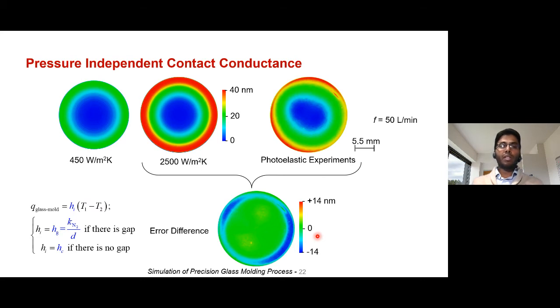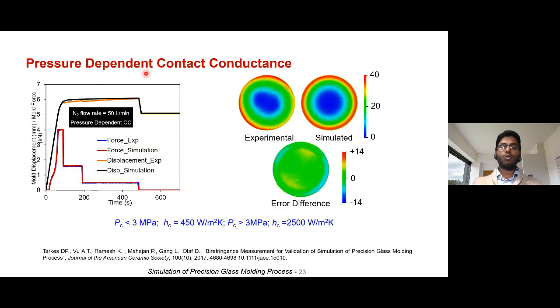But when we use pressure dependent contact conductance, as the pressing operation is being done, based on the contact pressure, we change the contact conductance value. We found out that for a critical value of 3 MPa, if you use a lower value below it and a very high value beyond 3 MPa, then we are able to match the birefringence information as well as the force displacement curve information, all whatever we get from experiments.